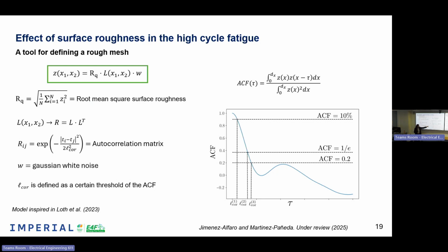And now when we represent it, we have different criteria proposed in the literature to measure the correlation length. The first one is when we consider that the ACF has decreased to 10%. The second one is when we consider that the ACF arrives to a value equal to 1 divided by e, the Napier constant. And then finally, the third one is when we consider that the ACF reaches a value of 0.2. So we have three criteria, and one of the objectives of our tool is, in fact, to reach a conclusion on which one is better for the predictions.